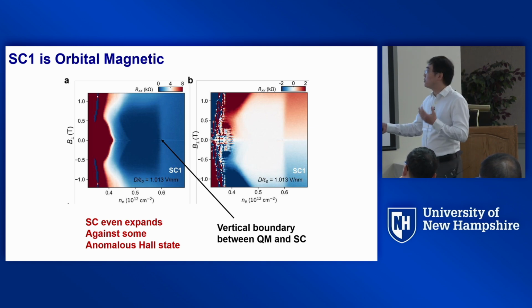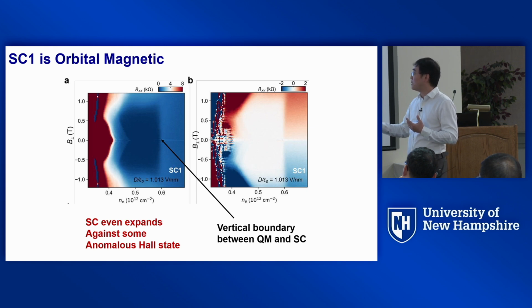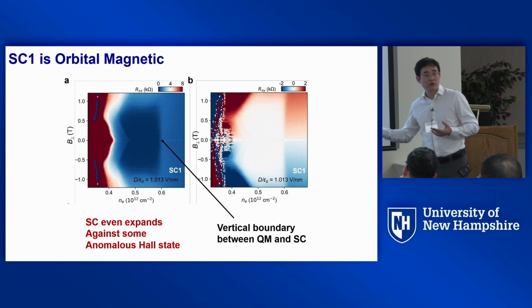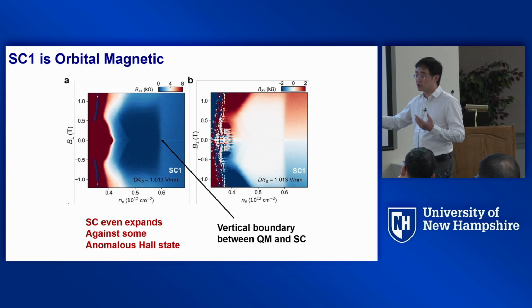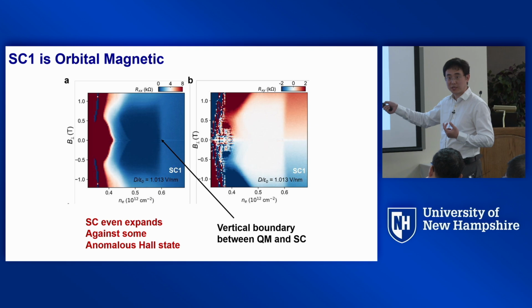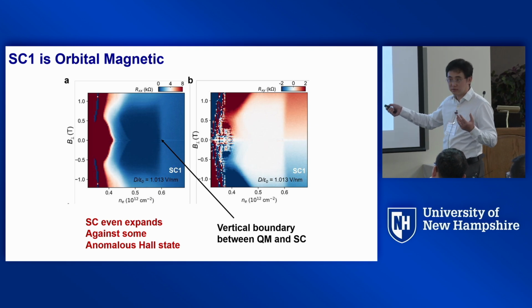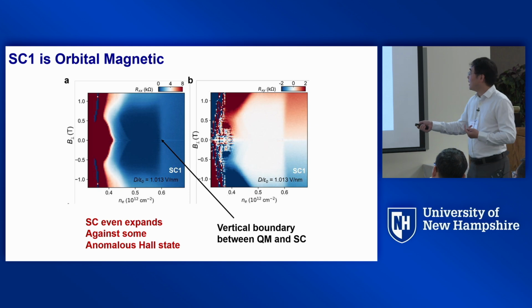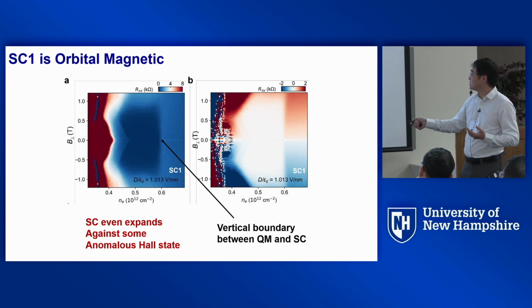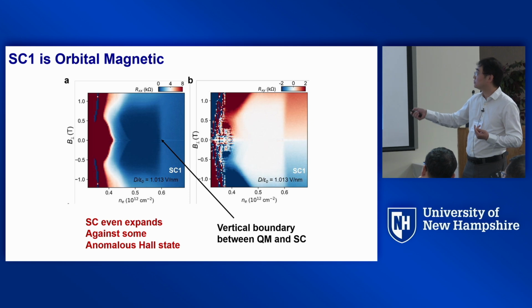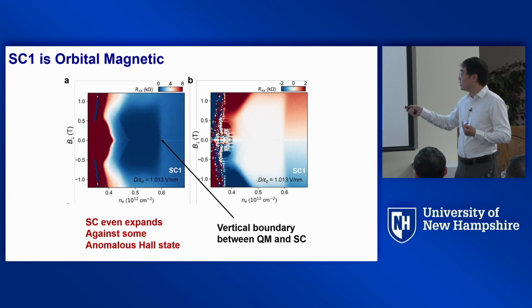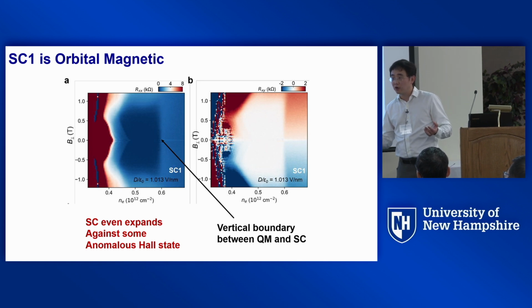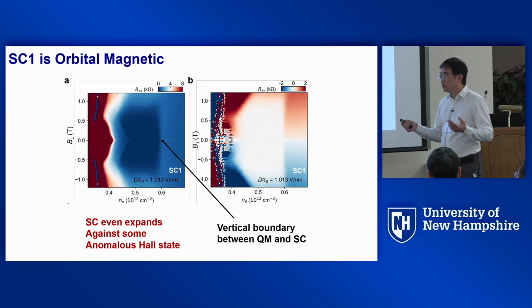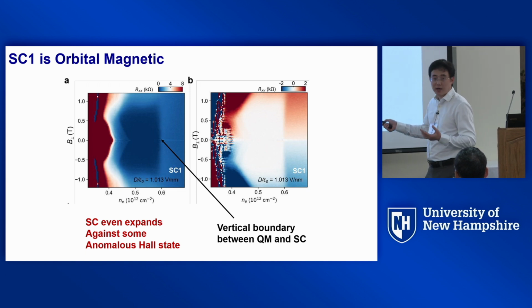And we're applying a very simple idea. If I apply an out-of-plane magnetic field, I'm coupling to the orbital magnetic moment of the quarter metal. If the neighboring state, superconductivity, is not magnetic, or not as magnetic as the quarter metal, then I would expect the boundary between them will shift towards the superconducting side, because the quarter metal is more favored at finite magnetic field. Okay? Well, what we really see is that on the right-hand side, this boundary remains pretty much vertical in both Rxx and Rxy. And that tells us immediately this superconductor itself is magnetic. Almost, or maybe exactly as magnetic as a quarter metal.